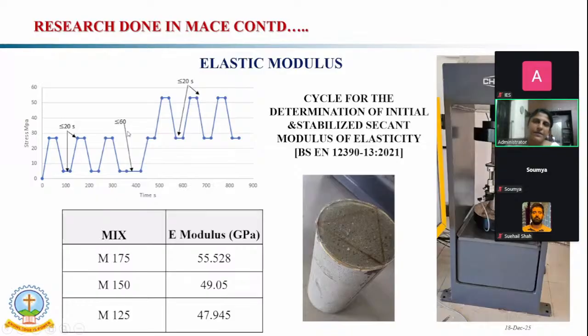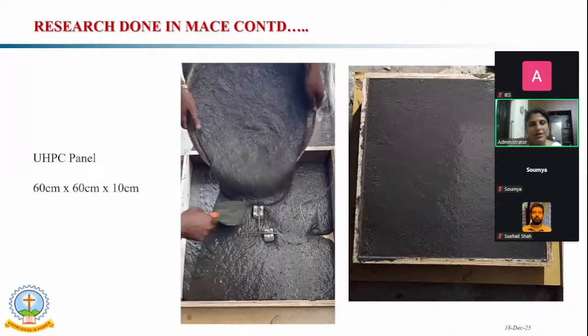In the first 3 cycles, for the M150 concrete, we have expected a stress of 150 Newton per mm square. The first 3 cycles are at 1/6 of the expected strength, and the last 3 cycles are at 1/3 of the expected strength. Then by using this, we got the E modulus of M125 as 47.945 gigapascal. M150 is 49 gigapascal. M175 is 55 gigapascal. We have followed the EN 12390 code. We have also checked a slab, a UHPC panel, with a size of 60 centimeter, using the servo controlled machine.